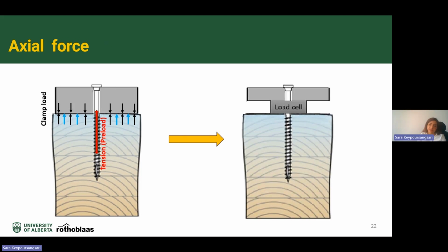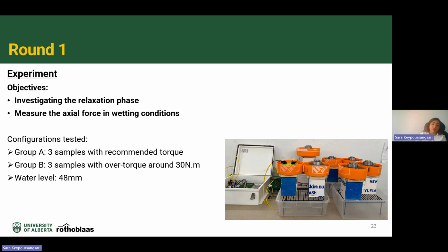Same as the previous steps, in order to measure the load caused by torque and moisture content change, we placed the load cells between the steel plate and our glulam, and we increased the moisture inside our samples. We divided this step into different rounds. In the first round, our objective was investigating the relaxation phase, and also we wanted to measure the axial force in wetting condition. We divided our samples into two different groups.